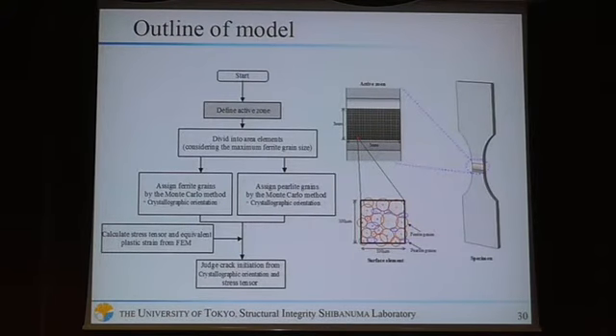First, where a crack can initiate is defined as an active zone. Next, the active zone is divided into area elements. Area elements are filled with grains by the Monte Carlo method, and grains are given crystal orientation randomly. Crack initiation is estimated from stress distribution from FEM and crystal orientation of each grain.